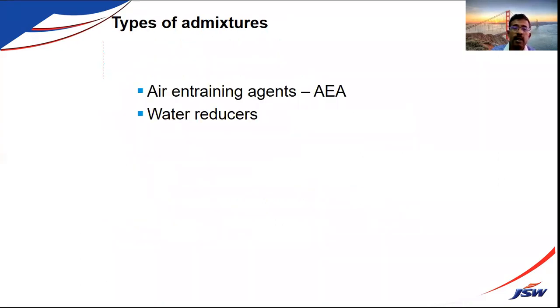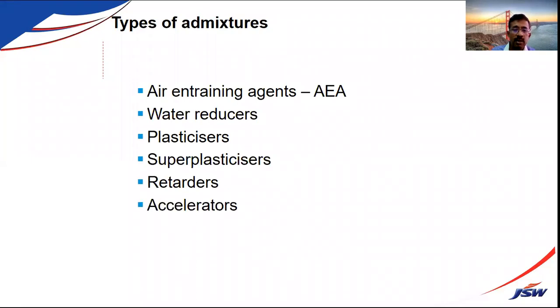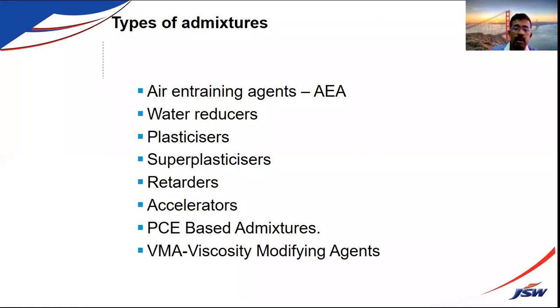There are types of admixtures: air entraining agents, water reducers, plasticizers, super plasticizers, then retarders, accelerators, especially used in the precast industry, PCE-based admixtures. So this is the family of admixtures used in concrete making based on the requirement. And VMA, viscosity modifying admixtures, especially to change viscosity, because the mix becomes very tight. If you are doing 500 kg plus cementitious material, the mix will be very tight, especially in self-compacting concrete. Adding VMA to have proper slump retention and flowability is very important. So VMA admixtures play a very important role in concrete making and foam concrete.